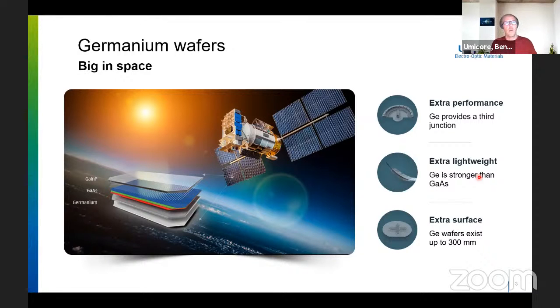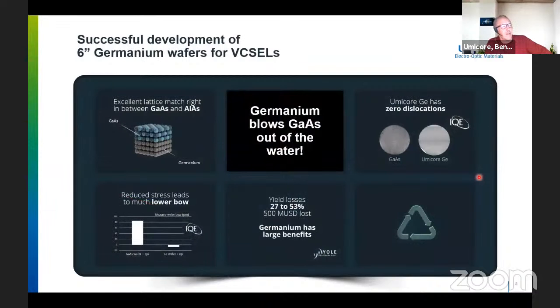So our wafers typically go at 145 microns thickness. And you can have sizes which are much larger than in gallium arsenide. Basically, germanium wafers are defect-free up to 12 inches, very similar to silicon. So I think these are a few important elements that are also becoming more and more important for VCSELs. And that's why we believe, and that's what I put here in the middle of the slide, that germanium is really going to blow the gallium arsenide out of the water. I understand this is quite a statement, but there are reasons to believe that this is going to be an important evolution. And so let me go through why.